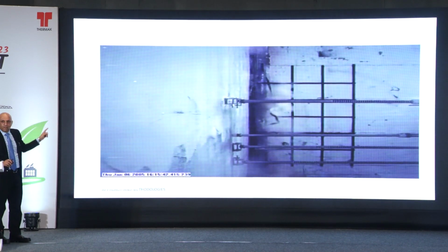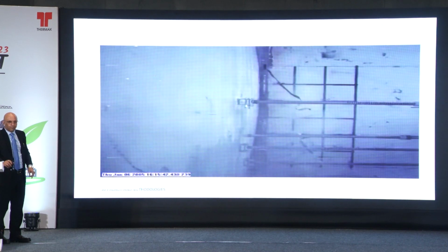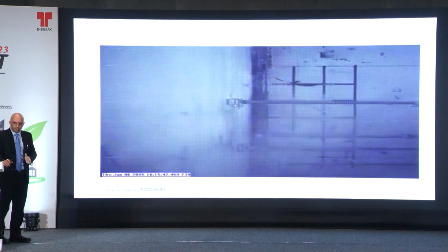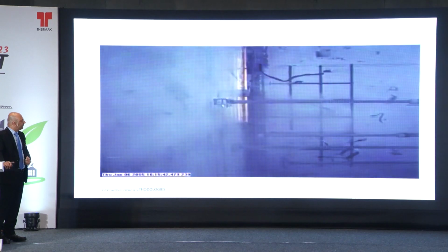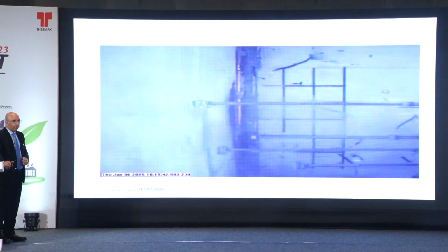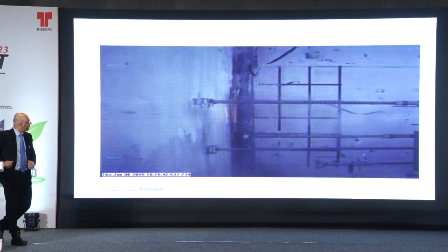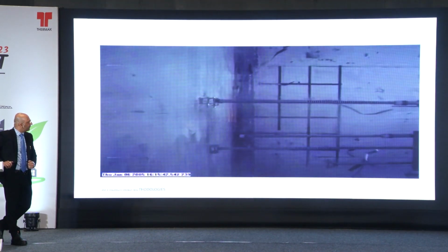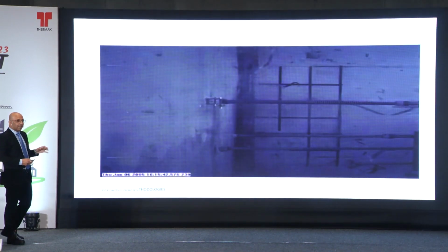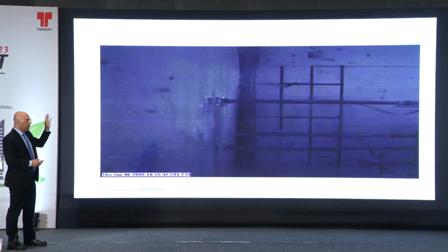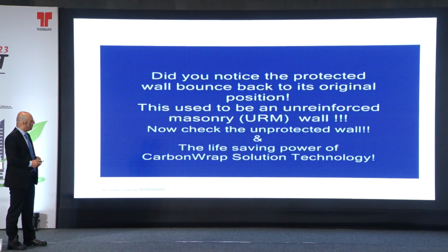Similar principle, now you can see from the side view, and this is a masonry wall. It deflected almost 4 inches on both sides and it came back to normal. The wall did not collapse except for the splatter on the wall. There was no damage observed. And you can see the brick wall which is unreinforced, it just collapsed.